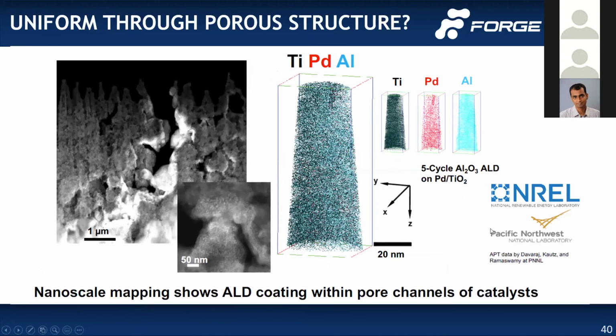So we did an overcoat of 5 cycles of alumina onto a palladium on titania catalyst. One of the questions is: is ALD uniformly deposited throughout a porous structure? This data here is showing that the alumina throughout a porous structure is depositing uniformly. As long as you are operating within an ALD window and let it run to completion, you will get deposition everywhere. That's how ALD works.